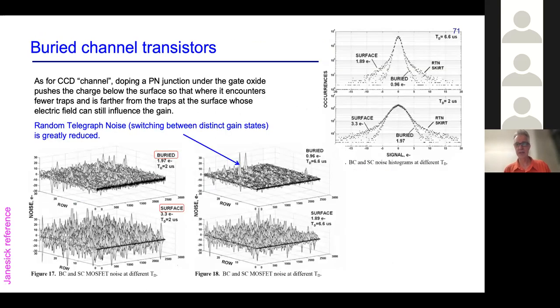So let's think about whether we can make this better. The first thing that CMOS designers had to do is to remember what was learned in CCDs, and that is that we don't want charge traveling along the surface where there are lots of traps. And this is true in the channel of a FET, not just in the channel of a CCD. And so this compares buried channel on the top and surface channel on the bottom, and shows that the noise is dominated by single electron traps, which lead to random telegraph noise.